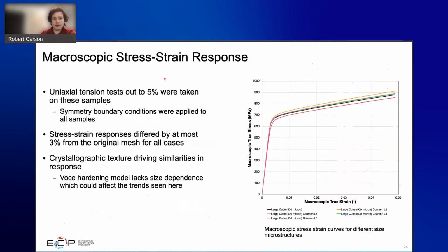So when we look at the macroscopic response, more or less all of them were the same. We only saw 3% deviation between all the different cases. And this was largely due to the fact that the crystallographic texture was largely the same between them. If we were just concerned with the macroscopic stress-strain curve, this tells us we can get away with fairly coarse meshes if we need to.